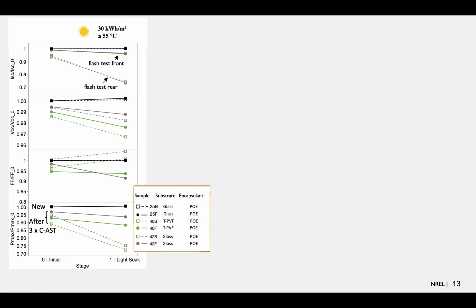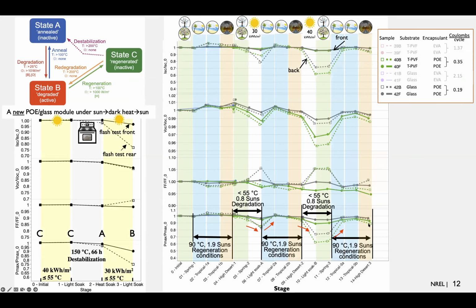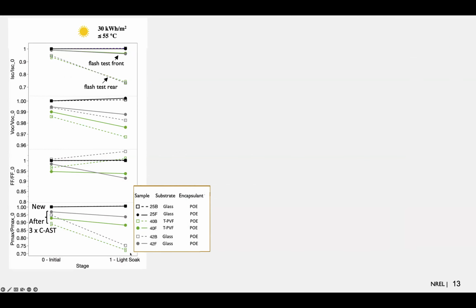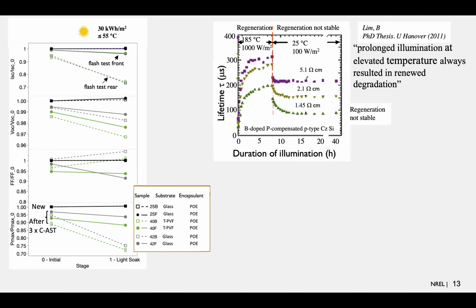So to understand this a little bit further, we took a new module and light soaked it ex situ, let's say in natural sunlight, and we took these modules at the end of combined accelerated stress testing, that's to say after high desert shown here, and put them out under light soaking as well. We see the new module has no degradation, but the modules that were exposed to combined accelerated stress testing do degrade under light soak. So this is a bit strange.